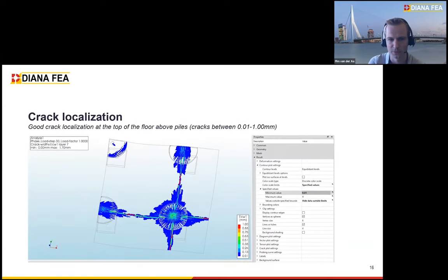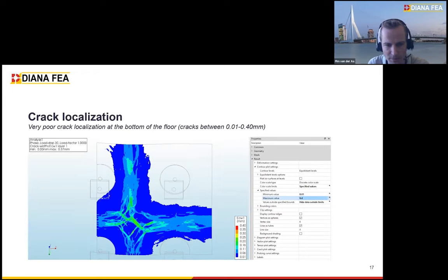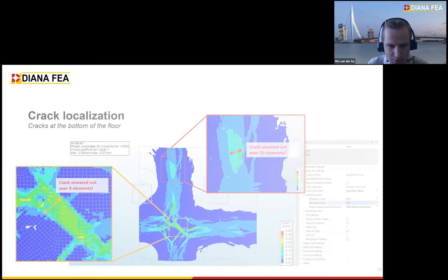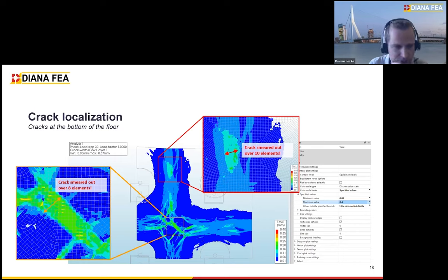And when we then perform the analysis, we can see that at the top of the floor above the piles, when we show the cracks, you can actually see that they're already quite nicely localized. However, if we look at the bottom of the slab, so that's mainly in the shell regions, also mainly the bending where the sagging moment is occurring, you can see that the crack localization is actually quite poor. And if we zoom in a little bit and also show the elements, you can see that some of these cracks are actually smeared out over 10 elements or 8 elements on the left side. And this is actually unwanted behavior for the reasons which were described earlier.